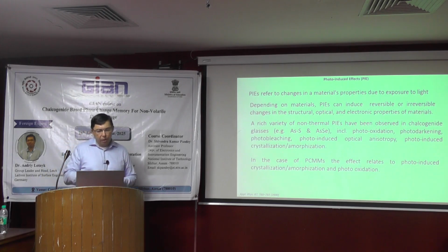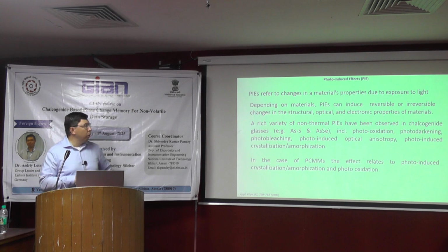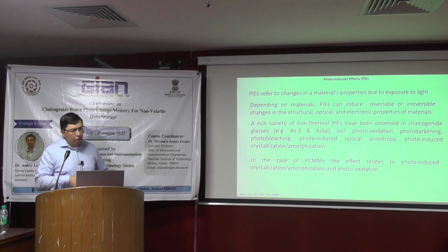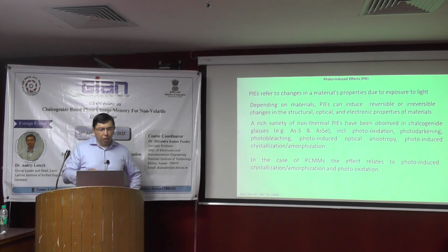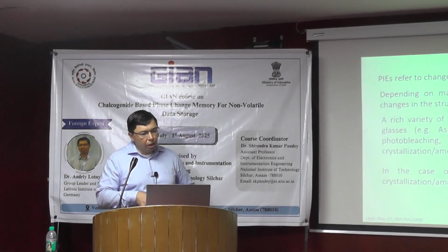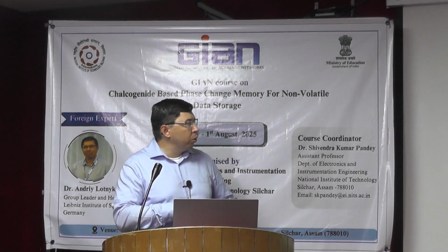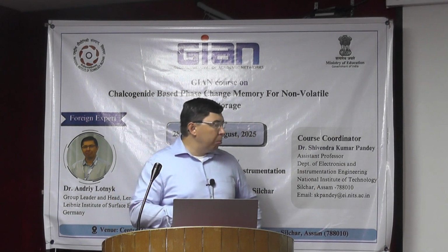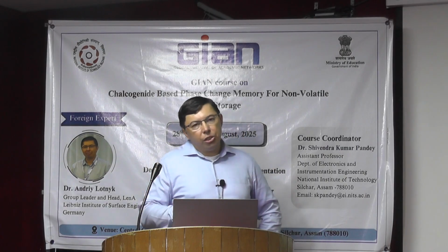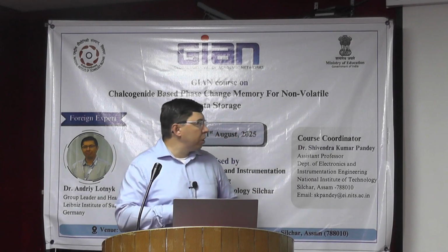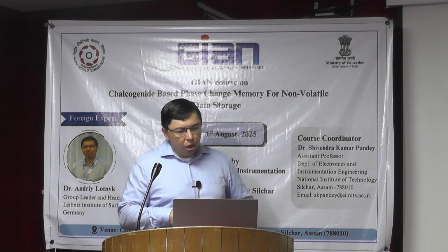This effect was shown for a variety of chalcogenide glasses like arsenic sulfide, arsenic selenide, and there are different types of effects. This is like photo-oxidation, photo-darkening, photobleaching, photo-induced optical anisotropy, photo-induced crystallization, amorphization, and in the case of phase-change materials, we also consider photo-induced crystallization and photo-induced oxidation.